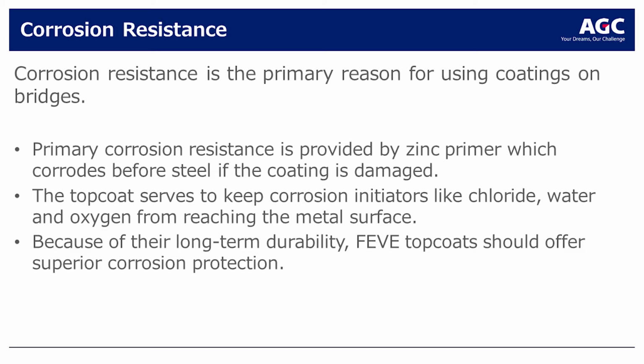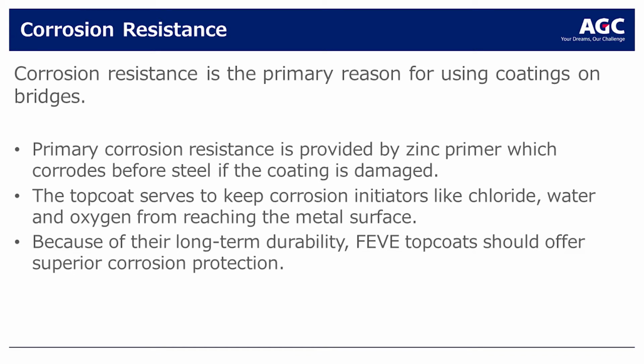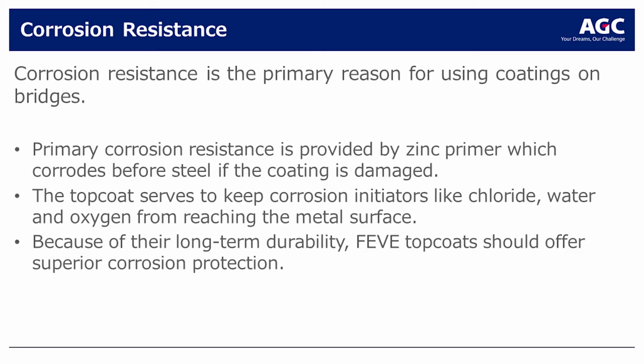So if the coating is damaged, what happens is the zinc corrodes preferentially to the steel. And usually you'll have some indication that you have damage and corrosion. There'll be a gray spot on the surface of the coating that'll indicate that the primer is degrading. That spot needs to be touched up before degradation happens. What the top coat is really doing, it's not only providing the appearance you're looking for, but it's keeping corrosion initiators like chloride, water, and oxygen from reaching the metal surface. So these FEVE top coats are superior in their longevity. So it seems logical that if they retain their coating thickness over long periods of time, they'll be a more effective barrier against these corrosion initiators.